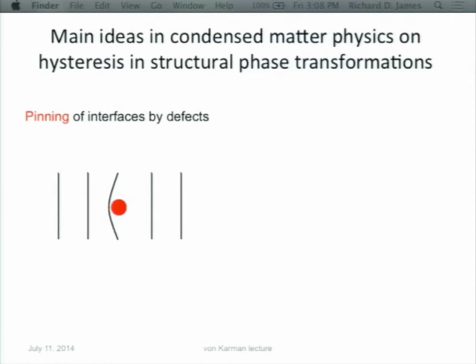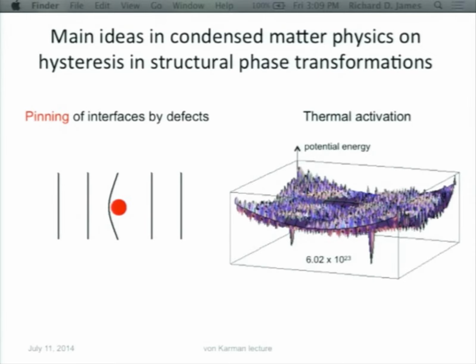so you can look in textbooks and find out what causes hysteresis, and I'll summarize the main ideas. Perhaps the most accepted idea is the pinning of interfaces by defects. When you have a phase transformation, an interface moves through the material. There are inevitably some areas of the material which are non-transforming, usually precipitates, and the interface gets stuck on these precipitates, and you have to lower the energy well of the new phase in order to have a free-energy-decreasing path and cause this interface to break through the precipitates. This is the origin of hysteresis, and it happens both ways through the phase transformation. That's probably the most accepted idea.